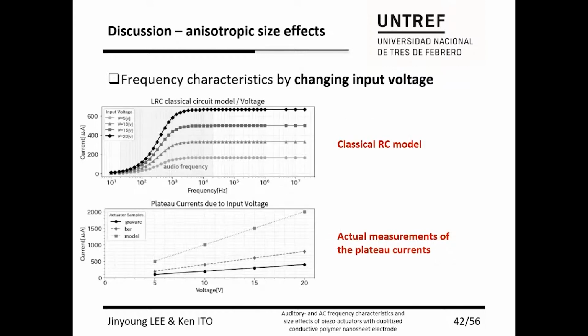We then took the plateau current values and plotted them on a graph. Although the conductivity differs between samples, it is proportional to the applied voltage in all cases, and the intercept with the vertical axis is close to the origin. From this, it is confirmed that the behavior in the high frequency range agrees well with that of classical resistance.